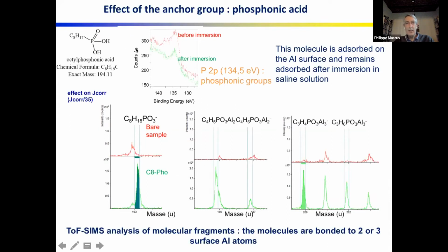Now we looked at phosphonic acid, this molecule, which is the octyl phosphonic acid, and we could clearly detect the phosphorus 2p signal both before immersion in sodium chloride solution and after immersion. So the conclusion here is that this molecule is adsorbed on the aluminum surface, and it remains adsorbed even after a long time immersion in the solution. And the same conclusion was obtained by looking at the mass spectra by TOF-SIMS, by looking at molecules that contain the phosphonic group. And we could also look at fragments containing aluminum atoms. In that case, we could see that the molecules are bonded to 2 or 3 surface aluminum atoms, in contrast with the carboxylic groups that were bonded to 1 or 2 surface aluminum atoms.